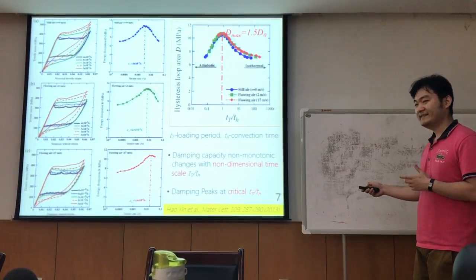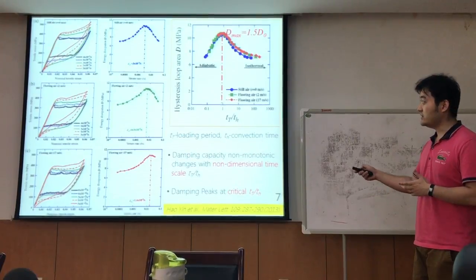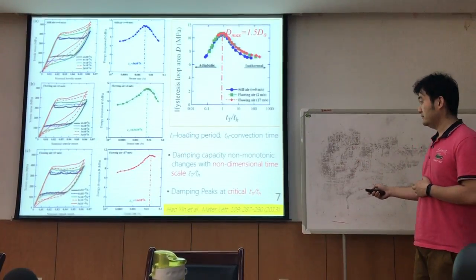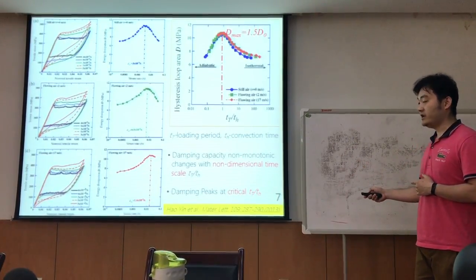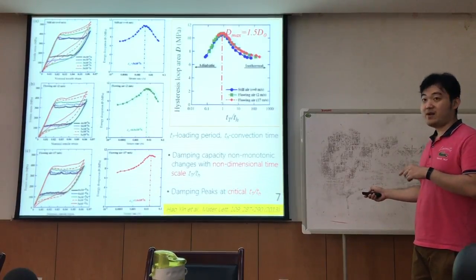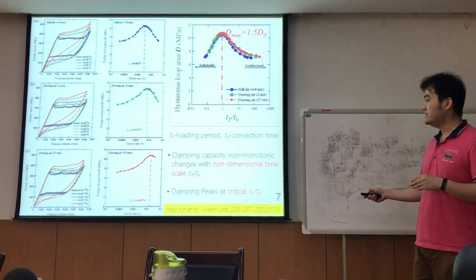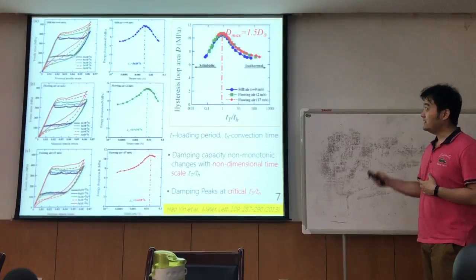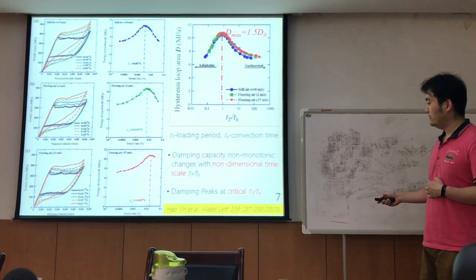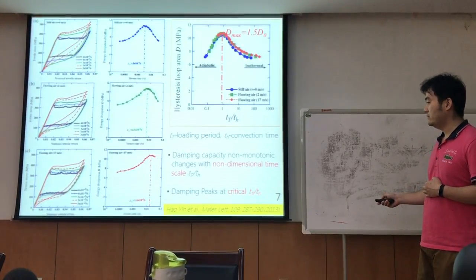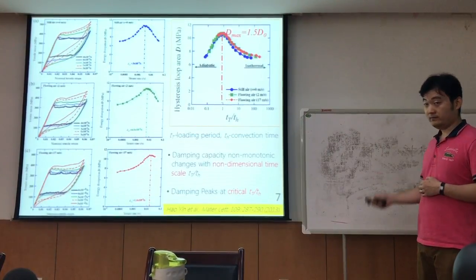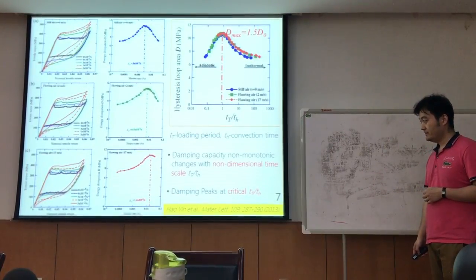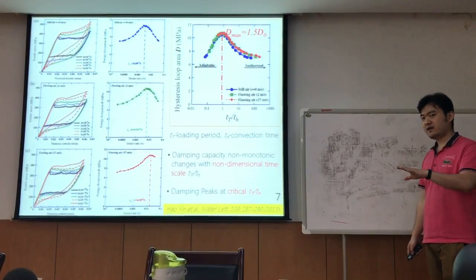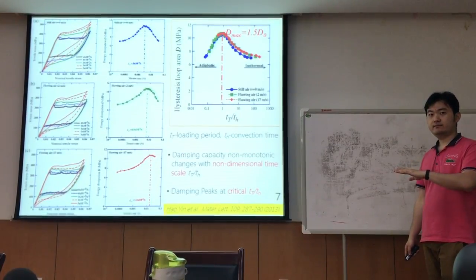The first one is that damping capacity, which is the energy dissipation here, changes non-monotonically with this non-dimensional time scale, Tt over Th. And the peak we have is at a critical Tt over Th. In this case, it's about 1. Okay, so this is for one cycle, loading and unloading.